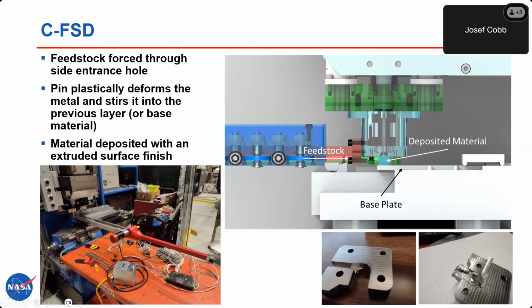And this image on the right is actually the first deposition we made with this process, and our feed rod got stuck. So we've made quite a few improvements there. But the feed rod coming in, you can see where the pin was stirring and what kind of deposited material comes out the backside. So I just thought that this lays out what's happening real well. We're pushing in a feedstock into the stir zone. We're just ramming it in there. This is stirring, plastically deforming the material, heating it up, right? And it's taking the shape of the opening on the backside.